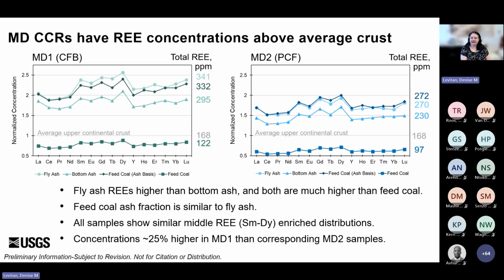So another thing that we see is that the relative concentrations of the different rare earth elements are similar in the different fractions, the fly ash, bottom ash, and coals, but then also between MD1 and MD2, which makes sense. They have similar compositions or similar shapes of these plots. They do have a similar geologic origin. They're not from the exact same seam in the exact same mine, but they are from the same general area of a single coal field. So they do have similar compositions. Although the MD1 is about 25% higher in concentration than MD2, that's consistent across the different fractions, including that feed coal.